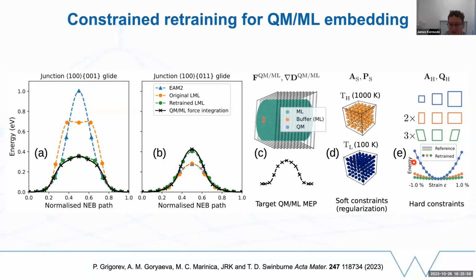And then we had some really hard constraints that in order for QMMM to work well, you need to make sure that you have really good elastic matching between the quantum region in the middle and the classical region outside. Otherwise, you might get reflection of phonons from that interface. So there's a hard constraint that exactly preserves the energy volume curve, the elastic properties, so that we don't reduce the quality of that elastic matching.